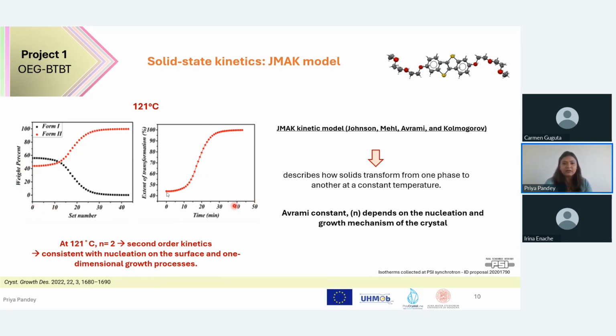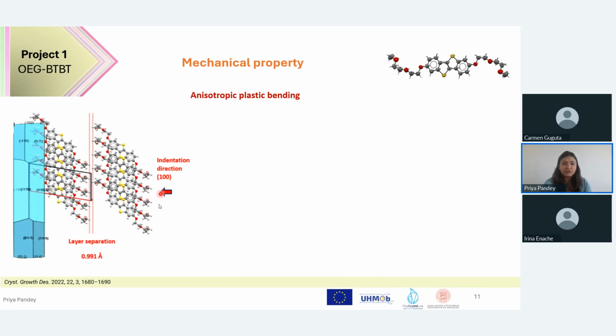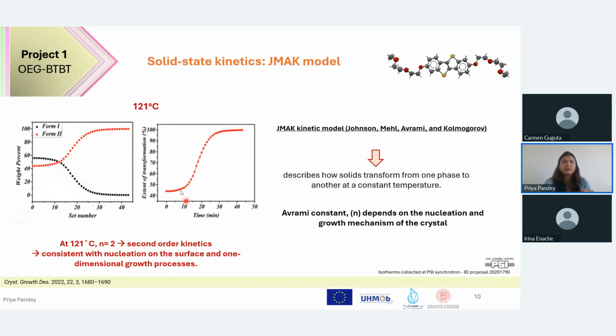And here you can see the extent of transformation, which follows a typical sigmoidal shape. The extent of transformation is very slow in the beginning because very few nuclei are forming form 2, while it's faster in the middle, where the nuclei that are already formed are growing, and simultaneously more form 2 is nucleating. In the end, it's again slow because very little untransformed form 1 remains.